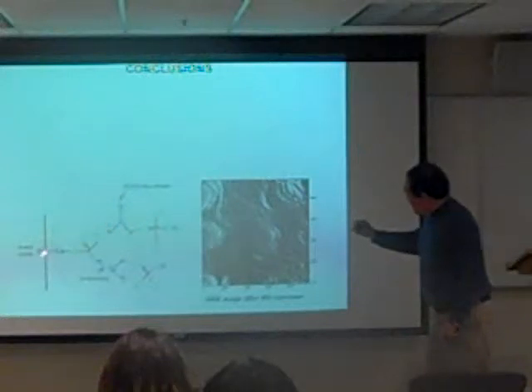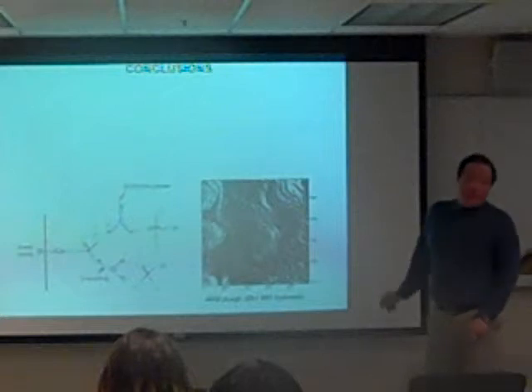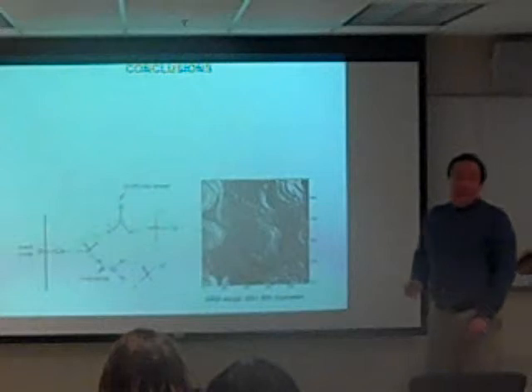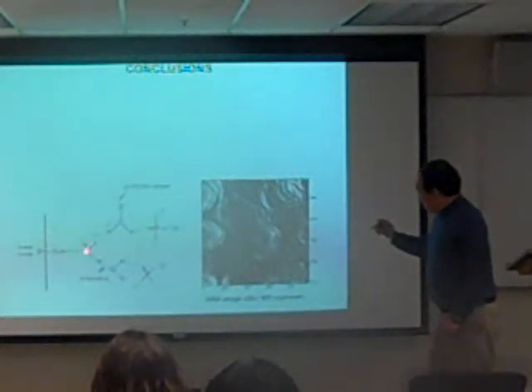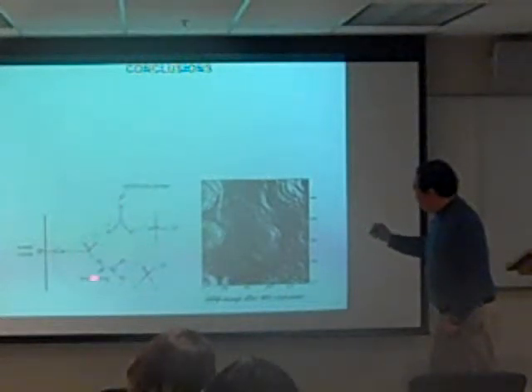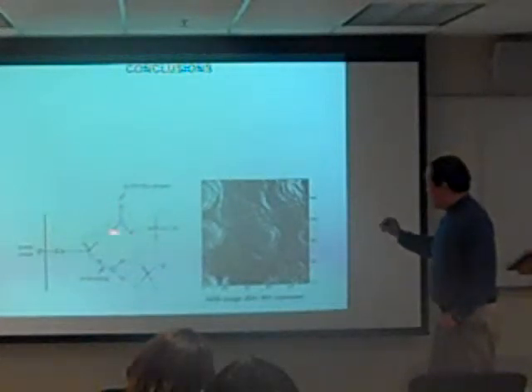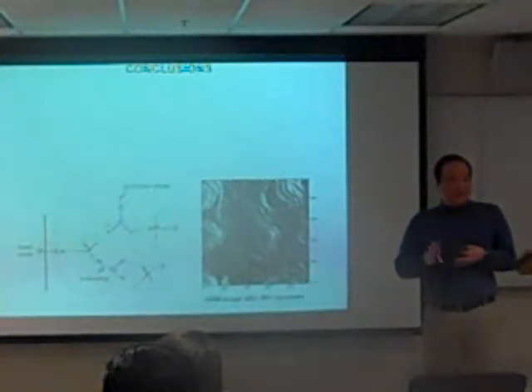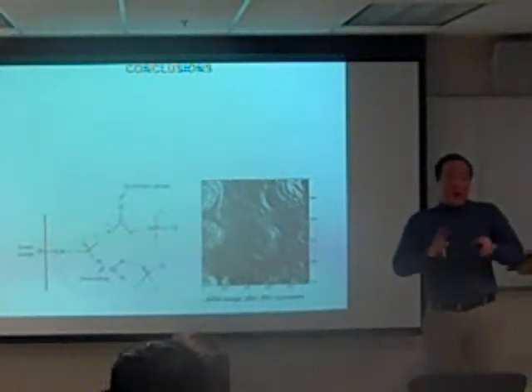And what we see here is basically a schematic that explains this structure. This is an atomic force microscope image where, after a 90-hour exposure, you can see some evidence for islanding on the TiO2 surface. And the way I've drawn this scheme here is that this is like a brushite-like phase, where basically we have hydrogen serving as the charge balance. And unfortunately, with XPS, you can't do analysis of the hydrogens. That's a limitation of the technique.